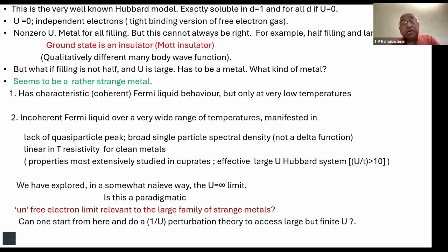It has a characteristic coherent Fermi liquid behavior at extremely low temperatures. On the other hand, it is an incoherent Fermi liquid over a very wide range of temperatures. And how does this incoherence manifest itself? It manifests itself in the fact that there are no quasi-particles. That is, momentum is a good quantum number, modulo the Brillouin zone vector. If you have an electron with a well-defined momentum, it should have a well-defined energy. It turns out that this is not true, but if it were true, then the spectral density would be a delta function. In reality, the single particle spectral density is very broad, so there is no quasi-particle.